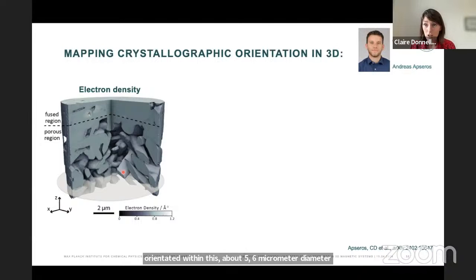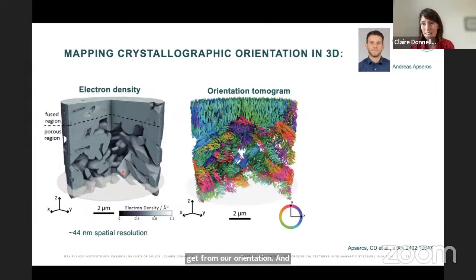But what we can then do is have a look at what we get from our orientation tomogram. Here you see immediately that the color indicates the orientation in the plane, so we can see a three-dimensional map of our crystalline orientation within our system. And not only can we see that we have a relatively complicated orientation map, but while some regions appear to be single domain, as we would say in magnetism language, other regions look like they would in principle be one piece, and they are actually composed of multiple crystal orientations.